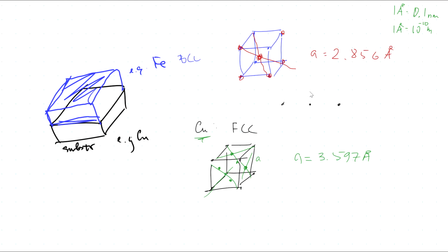Now what you can see is that if you take copper, and for example we have these atoms which are copper, and put iron on top, blue would be iron. If this atom aligns, then you see the interatomic spacing is smaller than for the copper. So what it means is that this atom would have, it is smaller. But there is interaction between atoms. They form the same crystal lattice when you put one on top of another. So what happens is that iron atoms move slightly out and copper atoms move slightly inward.